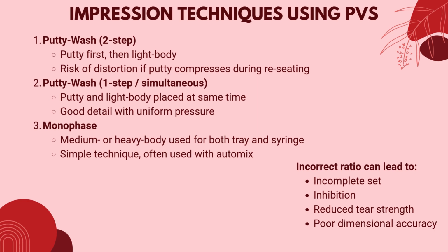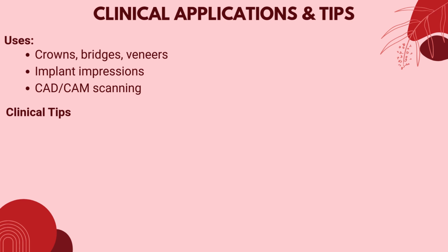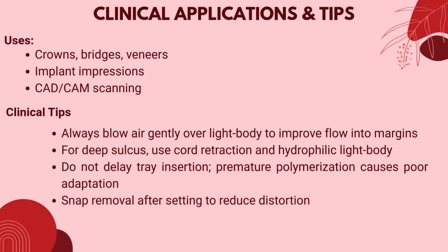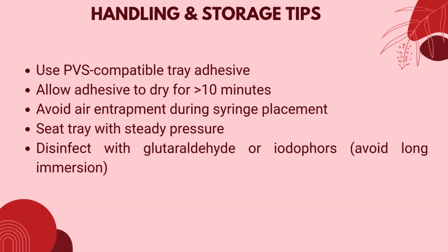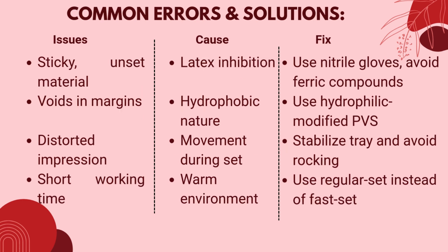An incorrect ratio of both base and catalyst paste can lead to an incomplete set of material, inhibition, reduction in tear strength, and poor dimensional accuracy. It is ideal for fixed prosthodontics, implant impressions, and CAD/CAM scanning. These are some clinical tips for handling. A compatible tray adhesive must be used for at least 10 minutes before loading. For disinfection, glutaraldehyde and iodophores are used, but avoid long immersion. These are some common errors, their causes, and solutions.